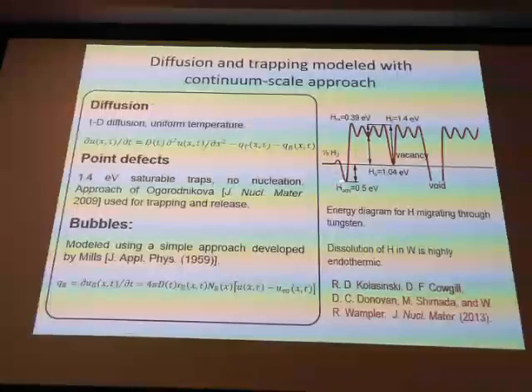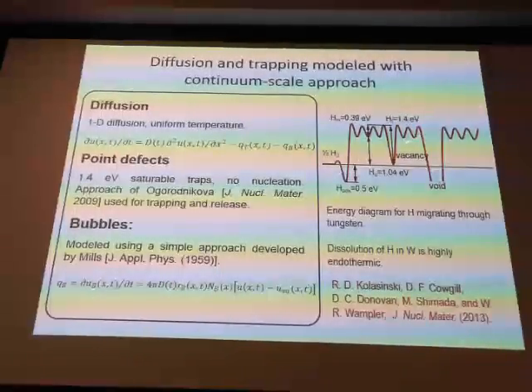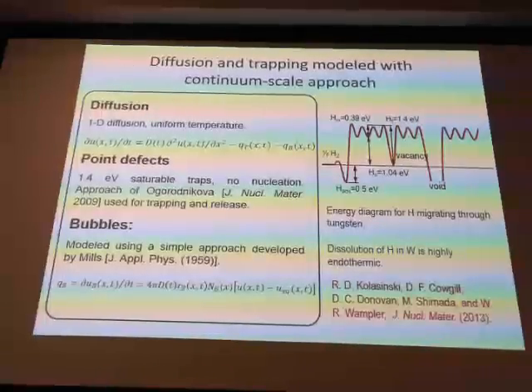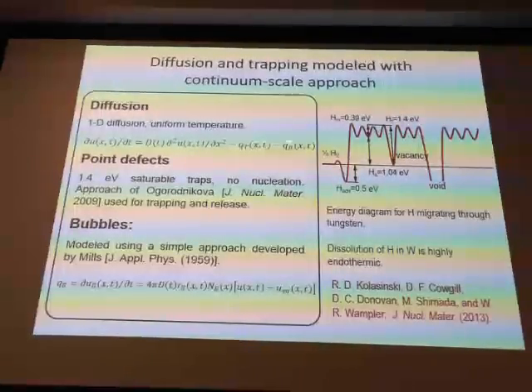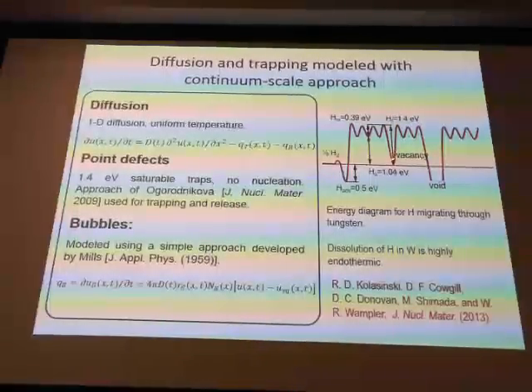And so this is sort of an energy diagram of the hydrogen migrating through the material. So the surface site, hydrogen chemisorbed on the surface, is very stable. But then dissolution of hydrogen into the material is very endothermic. And so there's a strong barrier to even getting it in there. But with plasma exposures, you're sort of overriding that. You're directly injecting it into the material. And it'll migrate around until it encounters a stable site, such as a vacancy.